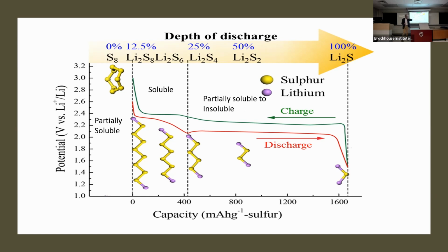Yeah. Such that when the volume expansion takes place and the volume decreases as a result of the reverse reaction, it doesn't lose contact, which it invariably does. Yeah. So this morphology construction is the challenge. It is really the work material scientists do all the time. You look at morphologies of your structures, especially in composites. Yeah, these are composite structures, and you need a binder to hold them together. Okay. And of course, we can see a lot of capacity is available at the later stage. But our aim perhaps is to just use the capacity up to here.